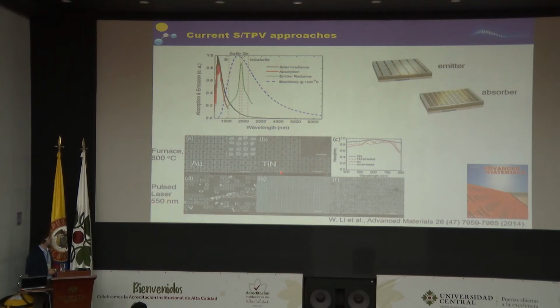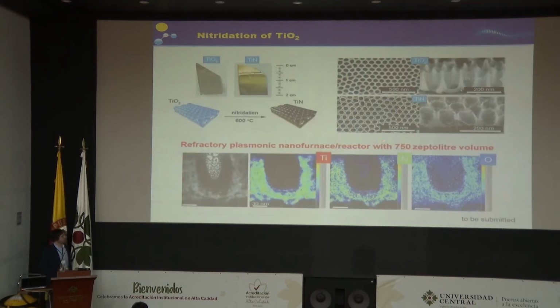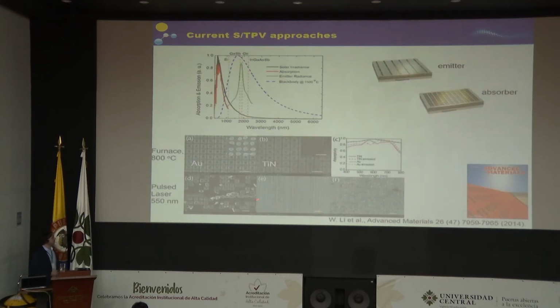And you can see that the titanium nitride doesn't change anything in the shape and organization of the metastructure. Otherwise, gold really collapsed and we lost some pieces. The shape is changed. And so this really demonstrates the outstanding performance of these materials for high temperature, extreme temperature regimes. And from this, this was the motivation for my work that I'm going to show you.